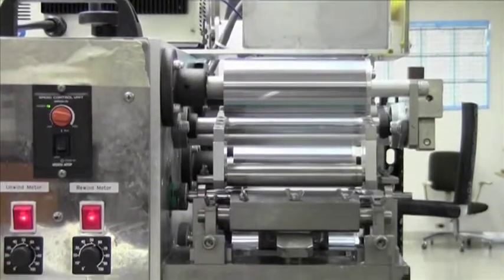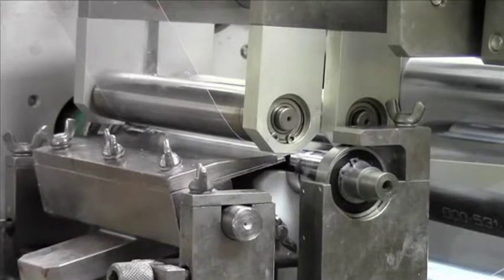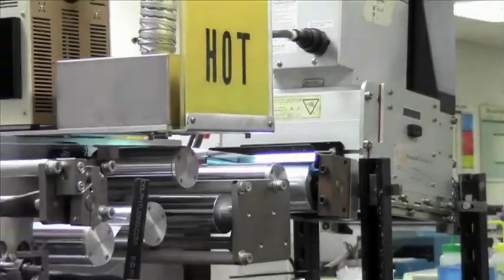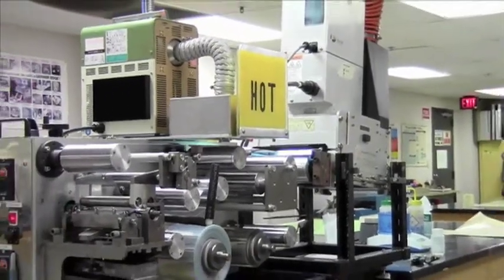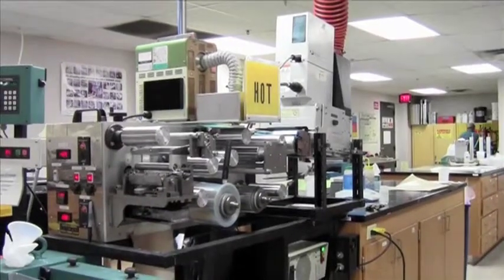Our lab pilot coater can duplicate much of our production capabilities, including gravure coating, corona treatment, and UV curing. It runs rolls of film 4.5 inches wide and requires very little coating, usually between 25 to 100 milliliters. This coater is an excellent step in the process that greatly speeds up the time to get a production-ready coating, while eliminating high costs from the process by eliminating the need of experiments on the production coaters.